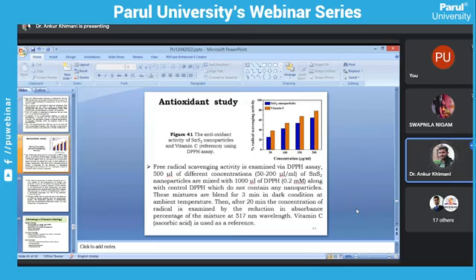Again, as far as the application part is concerned, we have done an antioxidant study. So the antioxidant activity of the SnS2 nanoparticle, and vitamin C as a reference, we took using DPPH assay. This is the percentage radical scavenging activity versus concentration profile. Blue is for the SnS2 nanoparticle and C is the reference, that is vitamin C. Free radical scavenging activity is examined via DPPH assay.